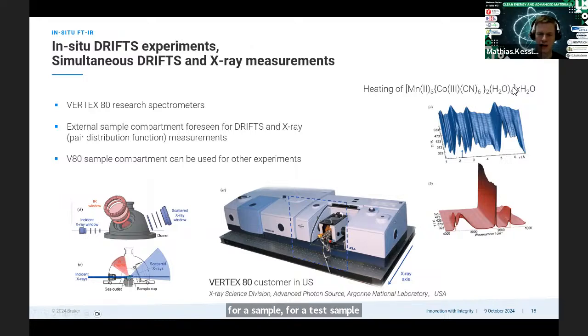And this is done here for a test sample, which is a complex inorganic complex, and it's a hydrate. And the hydrate will release water over the time. And in the IR spectrum, you can see how the bands of the water are vanishing. So they are going down. So at 3,500, this is the water. And at 1,600, this is also the hydrated water. And these bands go away. Then if we heat up the reaction sample.